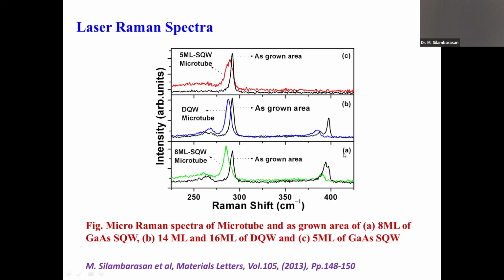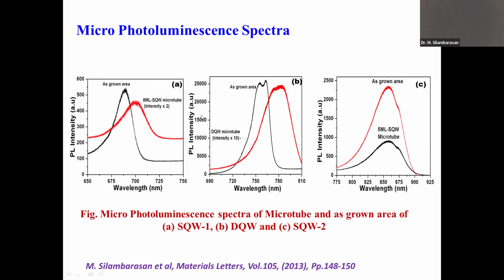And we further studied the laser Raman spectroscopy for the optical property. To study the optical property, we used the laser Raman spectroscopy for the semiconductor microtubes. And here you can see the single quantum well microtube and double quantum well microtube we used, and you can see their peak positions, as grown as well as the developed microtubes, they shifted because of the inbuilt strain present in the structure. Also we studied the photoluminescence of the fabricated microtubes. Here also we can observe the shift based on their inbuilt strain.